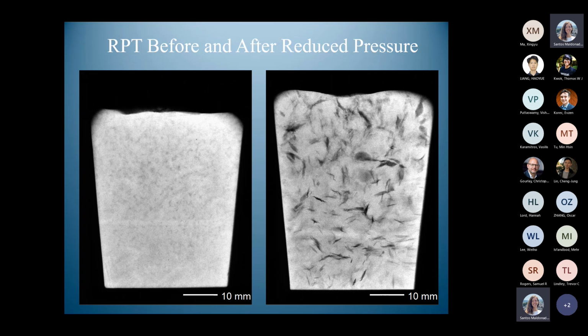And you finish up with a very curious crack. Now, I normally pass this around the audience so they can study this in detail. It's really quite interesting. You can see that it's the most amazing crack. This is not the sort of thing that metallurgy is accustomed to, but this is something very special to liquid metals. It is a unique defect structure in the liquid metal. And it's absolutely common because when you first pour, there's always enough turbulence to scramble up the bifilms such that they all finish in this compact state.